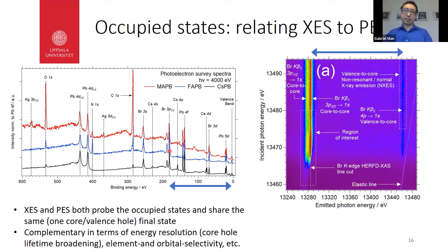So XES and PES are quite complementary, because they both probe the occupied states and they share, in principle, the same one core or valence hole final state, but they also have distinct advantages and disadvantages. For XES, the advantage is that we can selectively look at, in this case, bromine p states, but there's also pretty significant core hole lifetime broadening. With photoelectron spectra, we get all of the core levels referenced to the Fermi energy, but we don't have the element orbital selectivity. We do have better energy resolution because we don't have that bromine 1s core hole lifetime broadening.